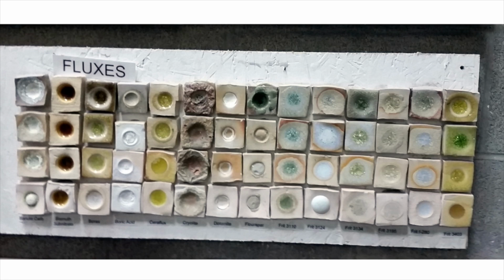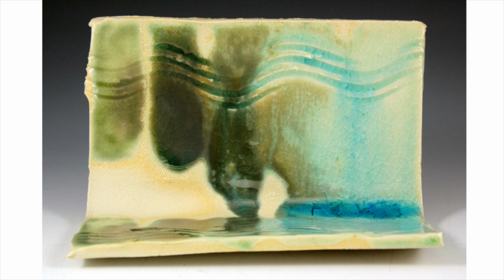So it didn't directly relate to the way we apply our glazes, which is so important. So we did the same test, mixing up the same amounts, except we added some water and brushed them onto the L-shaped tile of my design, as in this example of nepheline syenite plus copper carbonate, to see the test results easier, with additions of lithium carbonate, a very strong melting flux. This tile design tests the response of the influencing ingredient on a base, revealing how it behaves to vertical flow, horizontal pooling, over a slip, breaking over texture, and pooling in depressions, all on one test tile.